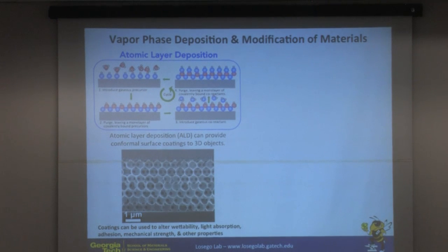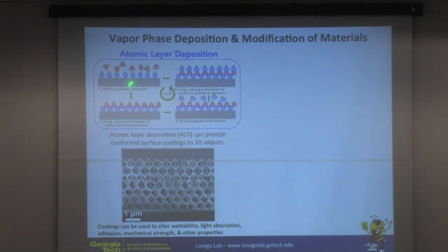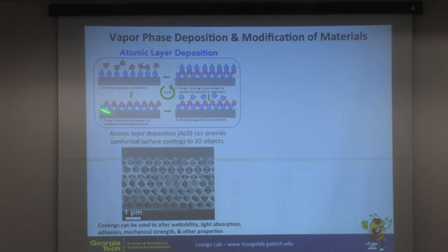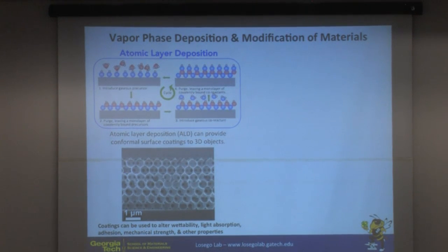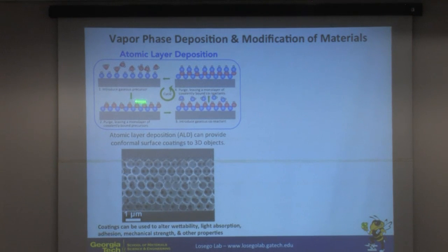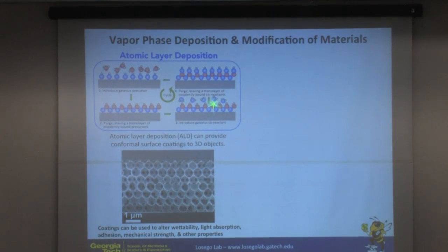Those are atomic layer deposition. Atomic layer deposition is a chemical vapor deposition method, except we're sequentially delivering the precursor. So we're not delivering both the precursor and the co-reactant at the same time as in a traditional CVD process. Instead, we deliver one precursor, we purge, remove that precursor, and we deliver the second precursor. And so that confines our reactions just to the surface so that we get a single reaction layer of our molecule on the surface, and then we purge off any excess and deliver our co-reactant and get, again, a layer-by-layer deposition that's conformal over complex three-dimensional architecture.